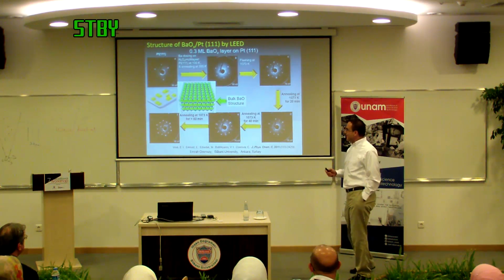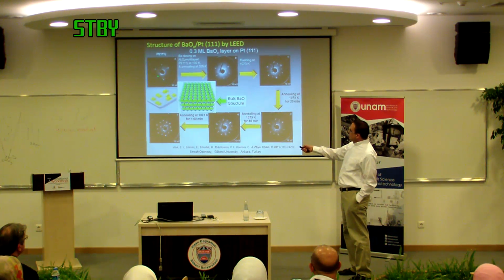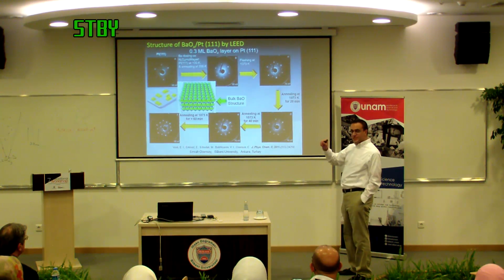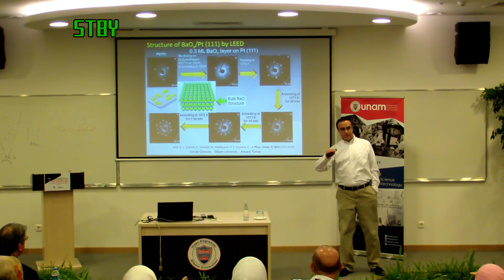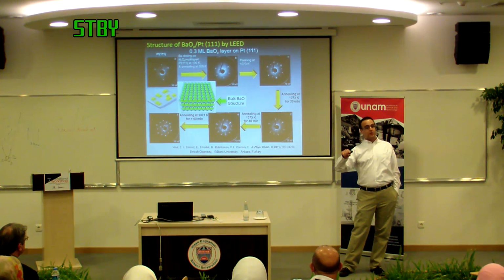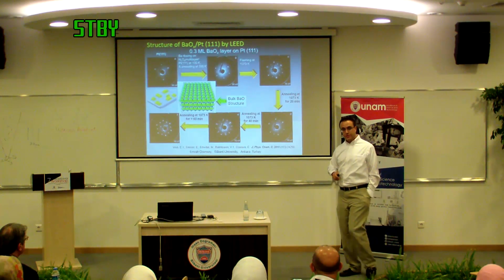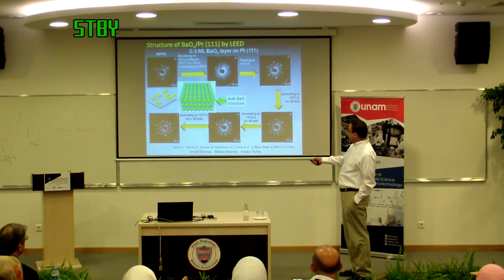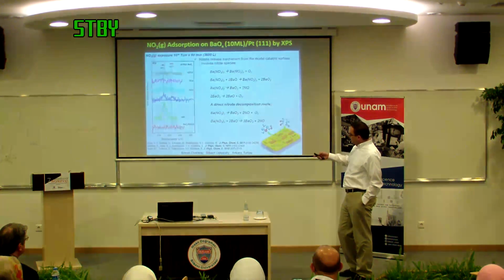7 years. But what is interesting is these barium oxide particles are not actually like these square-looking ones where it's a rock salt structure. In the nanoparticle form, these are surface diffraction, not X-ray diffraction. So the diffraction comes from the top monolayer of the nanoparticle. Electron diffraction using low voltage electrons. And you can see that diffraction patterns are very complex. We just analyzed this one. So they're very interesting 2D structures on the surface.